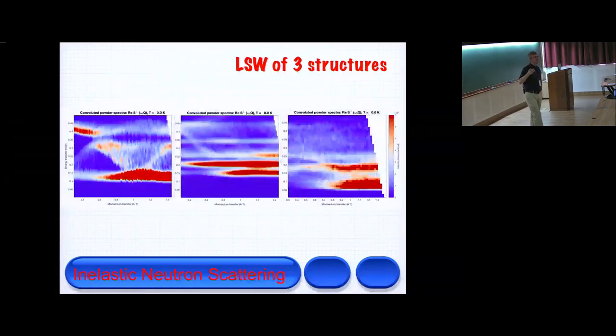Just plugging in the numbers of how we imagine the spins in the system, just the spatial correlations, for 3 different models, these are the calculated excitation spectra. So there's one with significantly high spectral weight at high energies, quite dispersive, and something down here. There's a model here where there's very flat bands at different energies, and then one finally over here where there's 2 bands. The elastic line, I'm sorry, is actually the bottom axis. This is 0 here, so all of this is excitations. So here there's 2 bands, maybe with some dispersion.